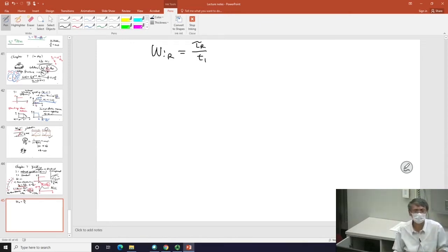It turns out it's just another, shorter time. Imagine all of a sudden you have no tube confinement, no entanglement. What would be the relaxation of that chain? I know I skipped a bunch of polymer physics here. It turns out that chain behaves like a Rouse chain, so-called. A Rouse chain has the feature that its relaxation time is proportional to molecular weight squared.